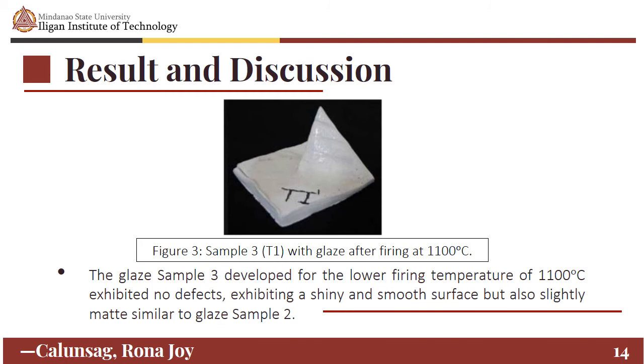Figure 3 shows the Sample 3, T1, with a glaze after firing at 1100 degrees Celsius. The glaze sample 3, developed for a lower firing temperature of 1100 degrees Celsius, exhibited no defects, showing a shiny and smooth surface but also slightly matte, similar to glaze sample 2.